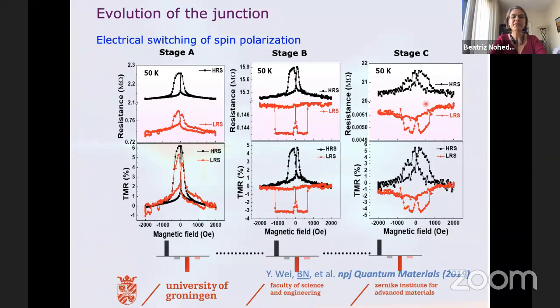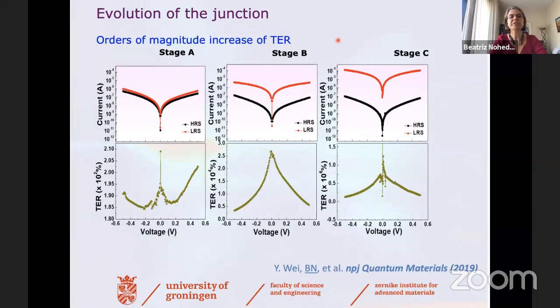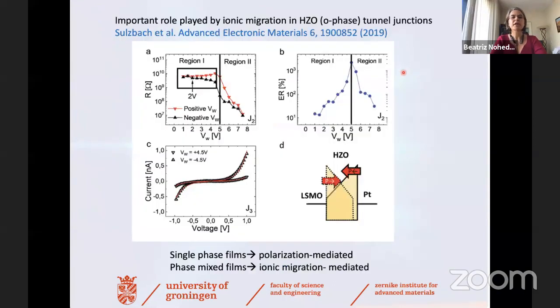And these changes are actually concomitant with changes in the tunneling electroresistance effect. You can see that this tunneling electroresistance effect, the change in resistance with polarization up and down, was not very much in stage A, but actually increases very much to 10^4% in stage B, and it reaches even 10^6% in stage C. So a huge change between the low resistance state and the high resistance state of the tunnel junction after cycling. So also similar effects have been found.